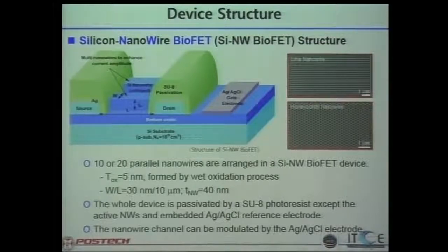But one thing that you got to keep in mind is if you have 2 microns apart and you have a 10 nanometer wire, it might behave like a bamboo pole, and it could just flex, or it could even break. Okay, so the students I had at Postec, they came up with a very clever idea. Instead of having these straight line nanowires, they also have a honeycomb-like nanowire. So essentially, it looks like a honeycomb, but it's not a big deal. When you do lithography, you use a CAD drawing, and instead of doing straight line nanowires, they do honeycomb on the CAD drawing, and then you do the etching. They can make honeycomb type nanowire.